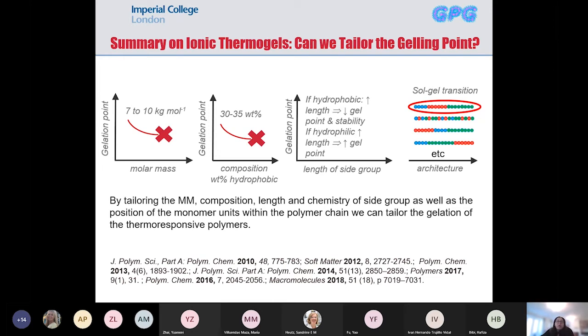Now, when we did try this dimethylamino-containing polymer, so the DMAEMA group, it has an amino group that is potentially charged. So at pH 7, it has a similar pKa, so at physiological pH, 50% of the groups will be charged. Normally when you have cationic charges within the polymer, they can destabilize the cell membrane, which is negatively charged because of the phosphate groups. So the ratio of the charge that you have on the polymer can potentially make it toxic. So even though DMAEMA polymers are used for drug and gene delivery because they are used in very small amounts, when we wanted to use it for thermogels, because our concentrations are much higher, they were too toxic.